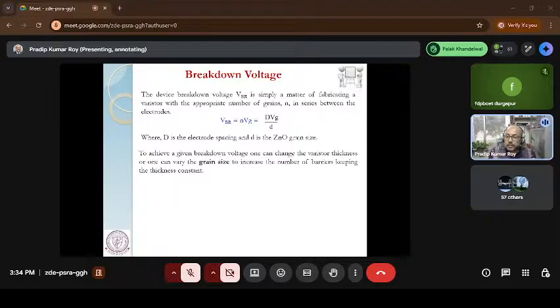So how do we increase the rating of the block? The number of grain boundaries depends upon D. Capital D is the thickness of the block, and small d is the diameter of the grain size. So if I reduce the grain size, the number of grain boundaries will increase. If the number of grain boundaries is increasing, that means a higher breakdown voltage is required to pass the electron from one grain to another grain. That means my rating of the block is increasing. So for the same height, same thickness, if I want to increase the rating of the block, the dimension of the grain size should be reduced.